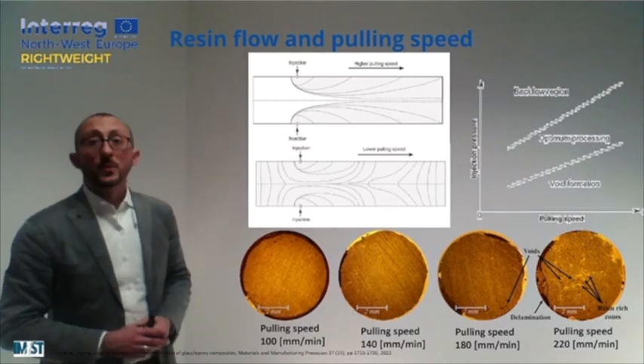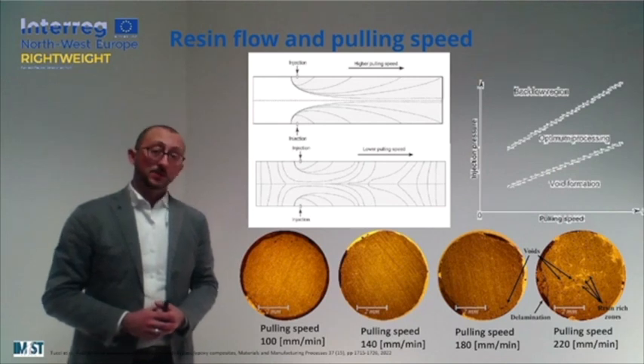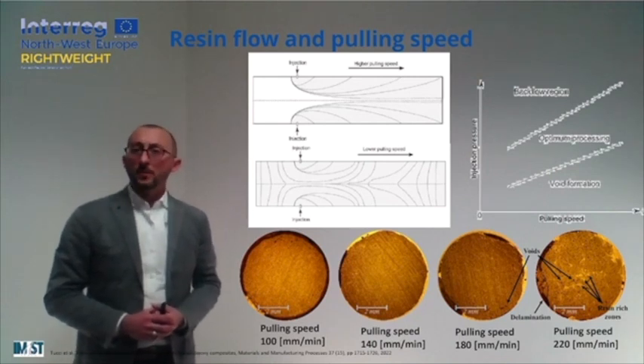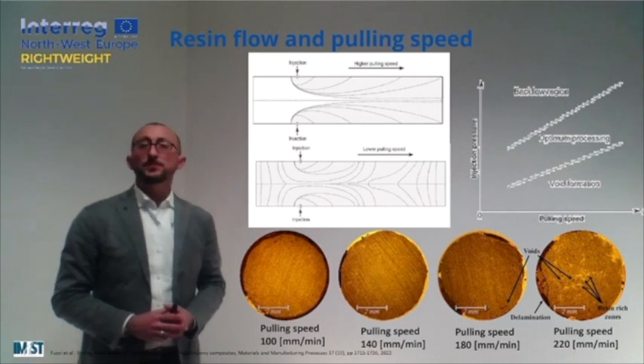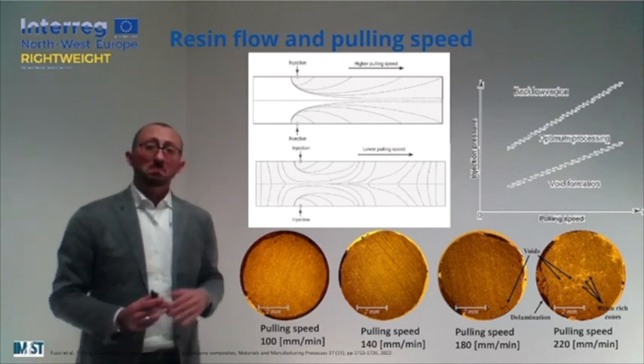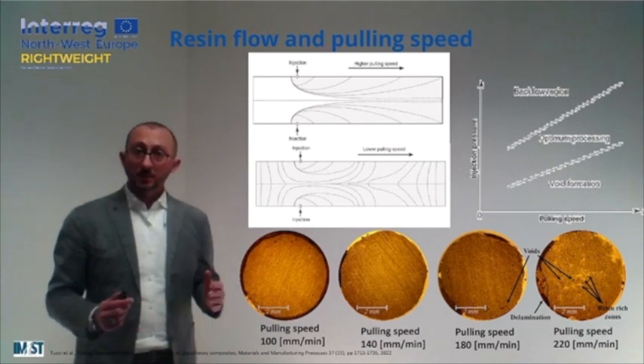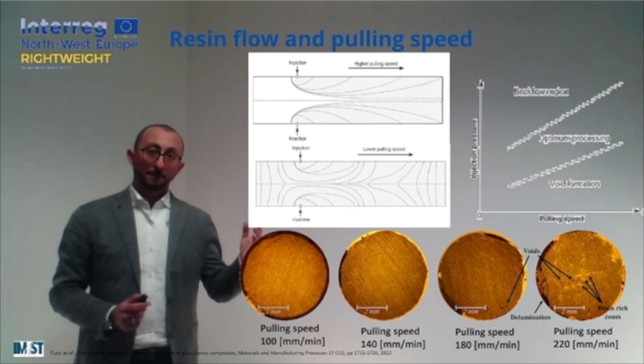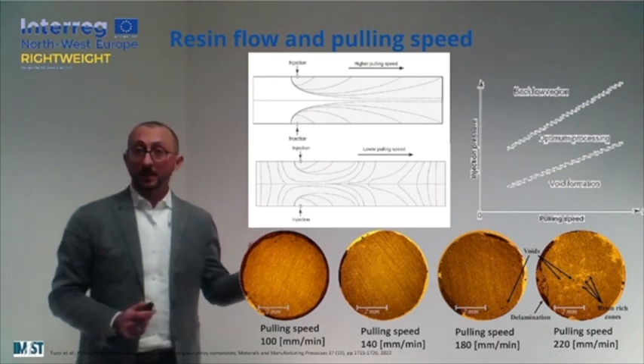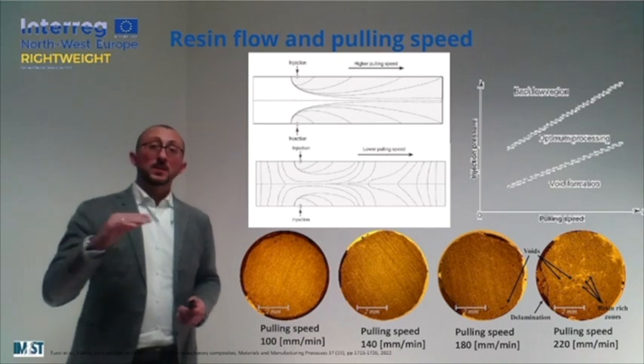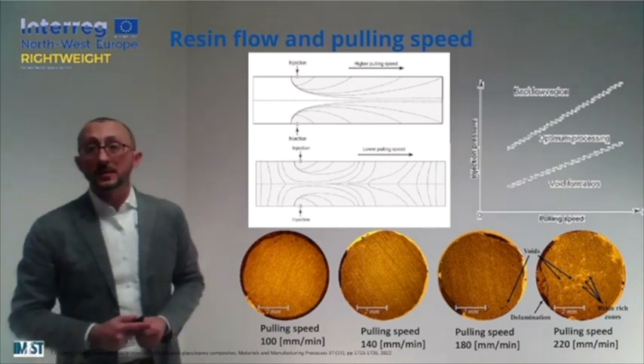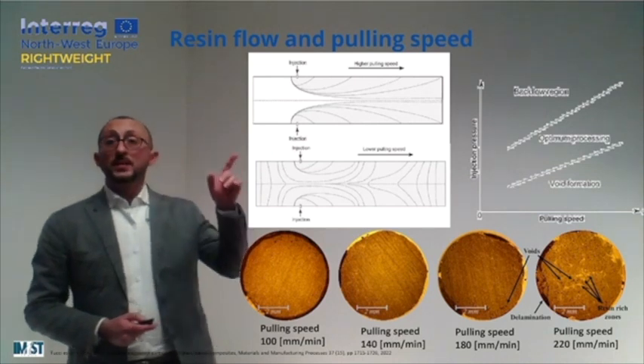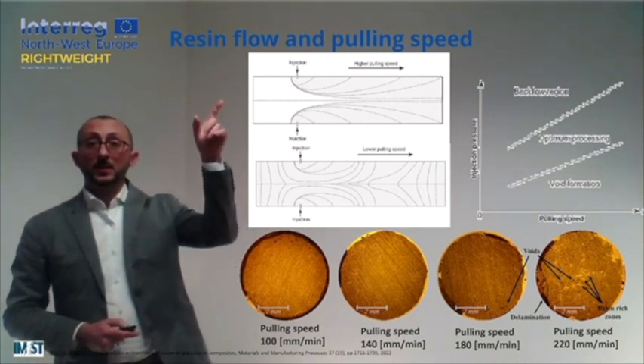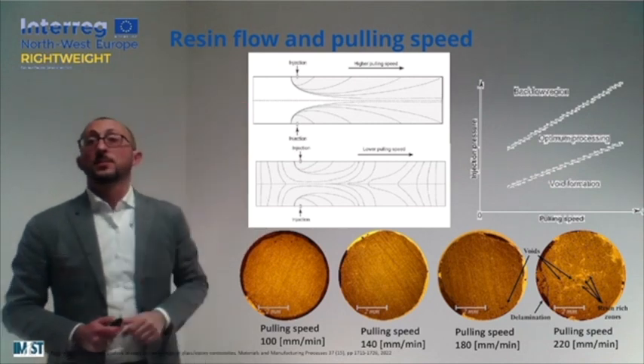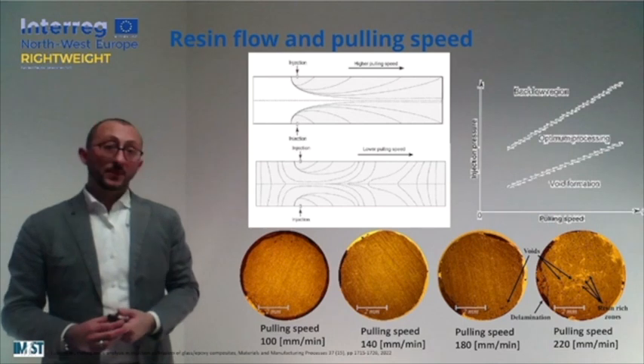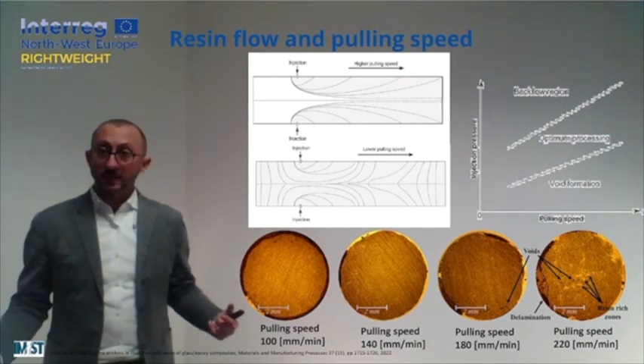So as a general rule, when we want to calibrate our parameters for a well-planned injection pultrusion process, we should try to increase the speed as much as possible, together with increasing the injection pressure. Of course, if the speed is too high and we are not pumping our resin at a suitable pressure, we can see something like this: the presence of some empty portion in our composite profile. And of course, in that case, we are just producing some scraps.